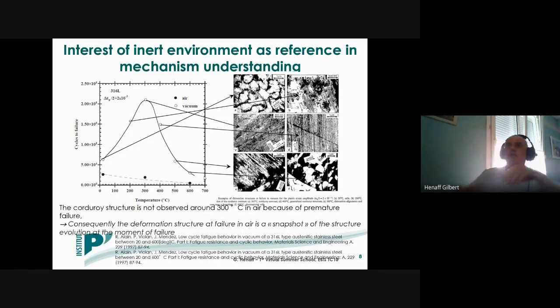However, when looking at the data obtained in vacuum, you can see that we have a maximum in the fatigue life, which is much higher, around 300 degrees C, and then decreases again. And at 600 degrees C, the difference between air and vacuum is not so large.